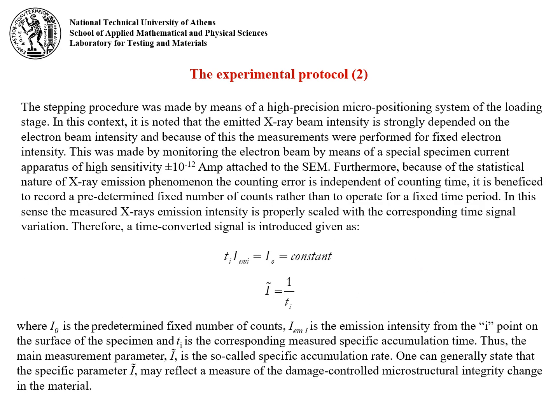The stepping procedure was made by means of a high-precision micropositioning system. The measurements were performed for fixed electron intensity. The measured X-ray emission intensity is properly scaled with the corresponding time signal variation. Therefore, a time-converted signal is introduced as the main measurement parameter — ī, the so-called specific accumulation rate — which may reflect the measure of damage-controlled microstructural integrity changes in the material.